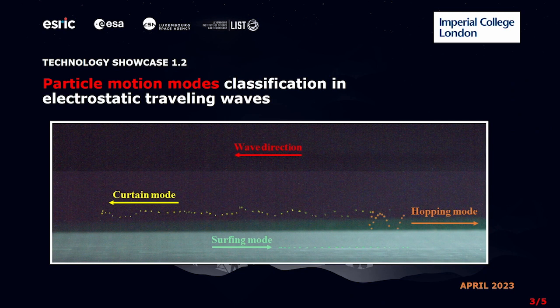In order to better understand how particles act in this field, we have done controlled single particle motion experimental research. By using a high-speed camera, we have observed 3 motion modes clearly. Here I will introduce them in detail. There we can see 3 different color trajectories. The smallest particle, in yellow, can navigate at a certain height without falling to the surface because the particle height is confined in a certain range, so it's called curtain motion mode.